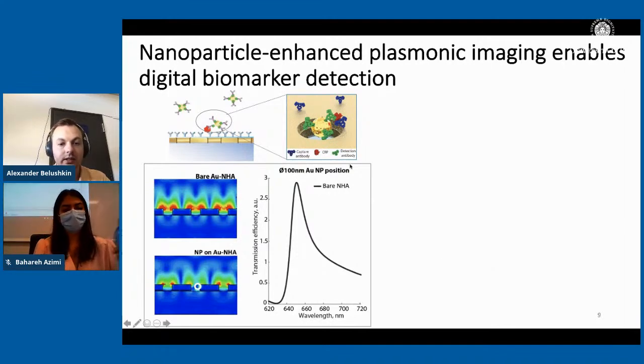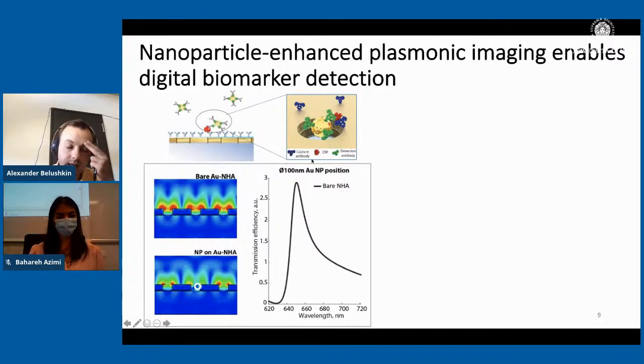What happens here is we have the plasmonic gold nanohole array, and we functionalize it with the first set of antibodies, called capture antibodies, specific against the antigen of interest. Then we take the gold nanoparticles and we functionalize them with the second antibody, which is called the detection antibody. It's against the same antigen of interest, but a different epitope. So basically, the two antibodies can bind at the same time.